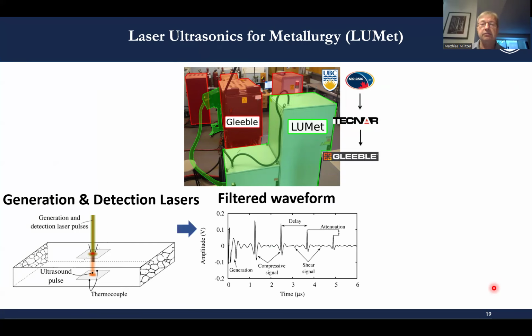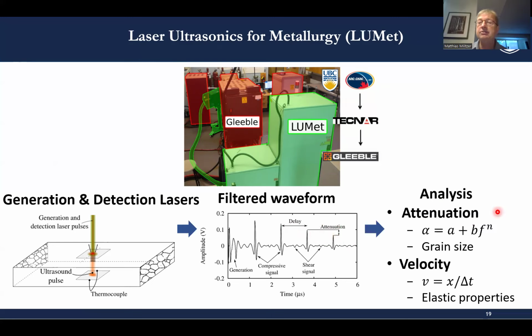And we get waveforms, these compressive signals, we have a delay time between the signals, and we see also that the amplitude is decreasing. So attenuation is another measurement result. The attenuation spectrum is a function of frequency, and we can relate it to the grain size. So this factor B is grain size dependent. And then the velocity is obtained from the delay time, because we know the thickness of the specimen, and the velocity is related to the elastic properties of the material. So when the elastic properties change,